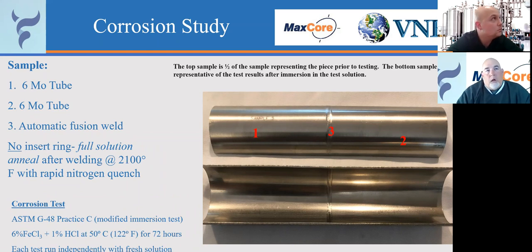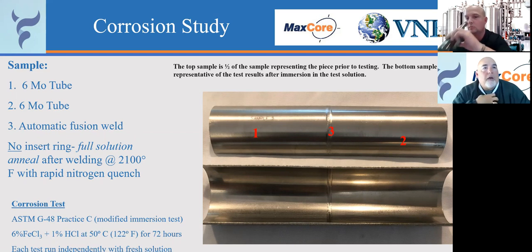Now, the only reason we talk about this is because this isn't something you can typically do in a field application if you're doing a welding of tubing and piping put together. But what happens is we take this in our applications in a fabrication setting like a fitting manufacturer, for instance, like us. If we were going to take an elbow and we were going to make a weld by clamp elbow and we had 100 of these things to make, we could do a straight fusion weld on that, send that whole batch out for annealing, and be less expensive when it comes to the fabrication over doing a weld insert ring at each of these locations. So in those types of applications, that's where the solution annealing comes into play. If you're going to do one or two fittings, then in that particular case, it might be more advantageous to use the weld insert ring and do those welds.